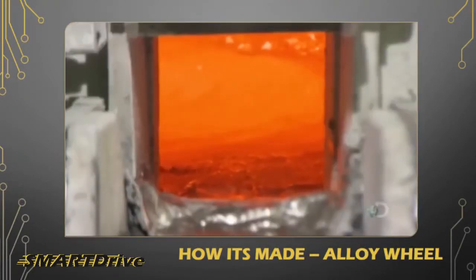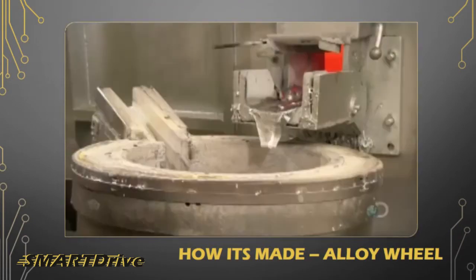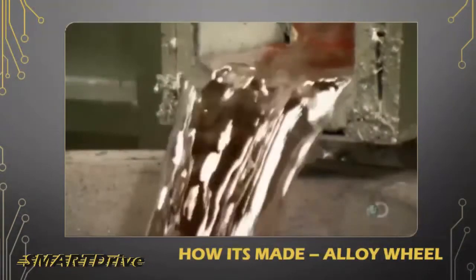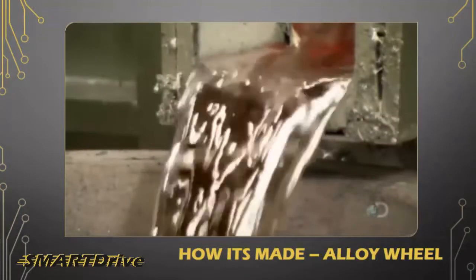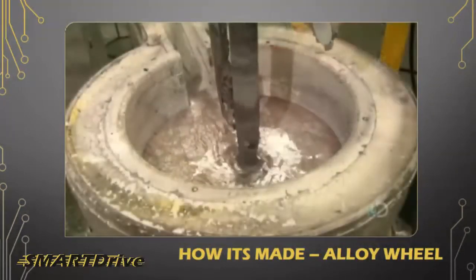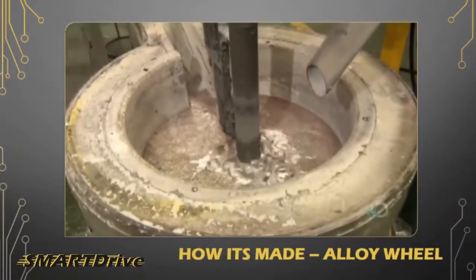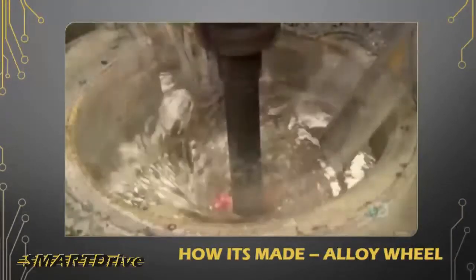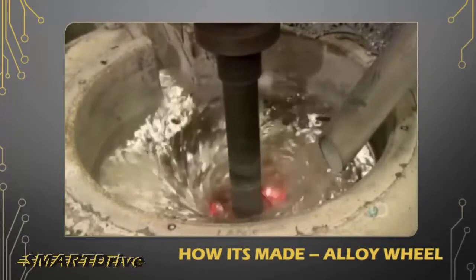A furnace heats the ingots to 750 degrees Celsius. They liquefy in about 25 minutes. The molten aluminum then flows directly to a mixer, in which they inject argon gas, which enables them to remove the hydrogen. This increases the density, making the aluminum less porous when solidified.